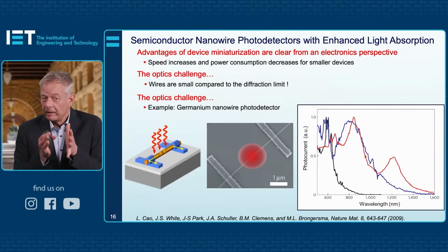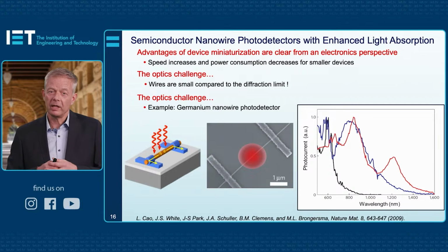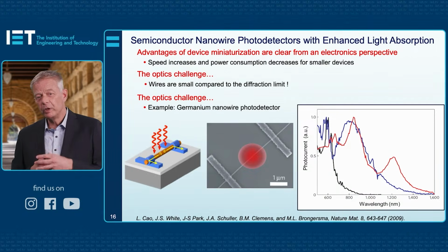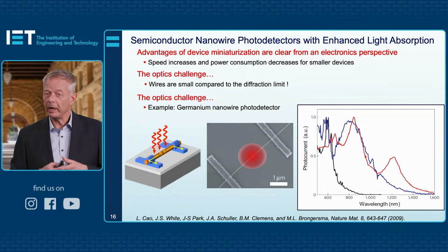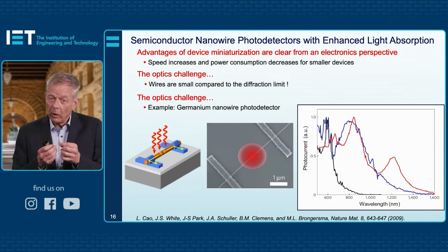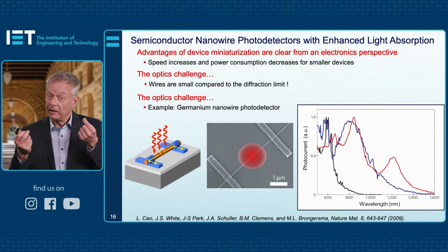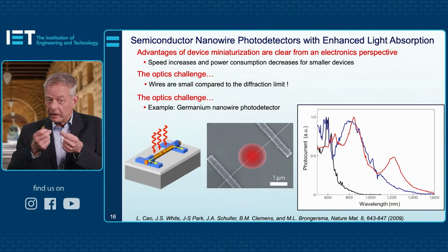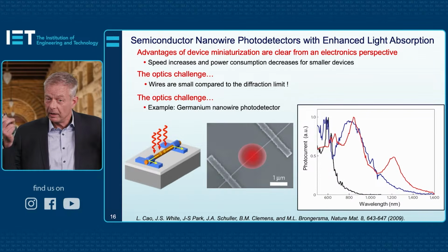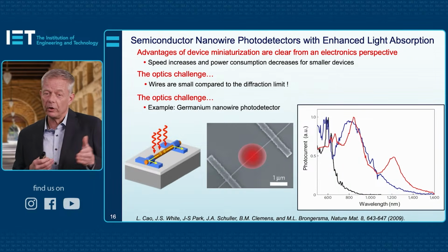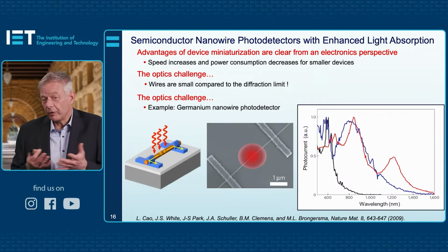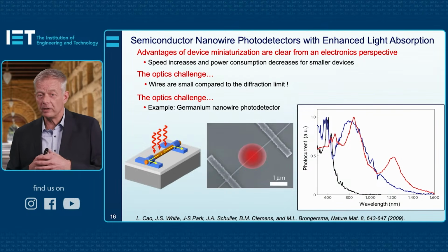Will all of the light miss this wire, since the spot size is so much bigger than the wire? Well, it turns out resonances can come to the rescue. If you do this experiment for a germanium nanowire, which has a very nice high refractive index, and you plot the photocurrent, which is produced by light being absorbed in the wire to produce excited negative electrons and positive holes that we can pull apart via the electrodes to produce current, and plot that current versus wavelength for different nanowire sizes, again, we see resonances.